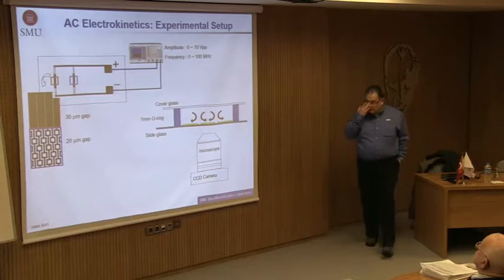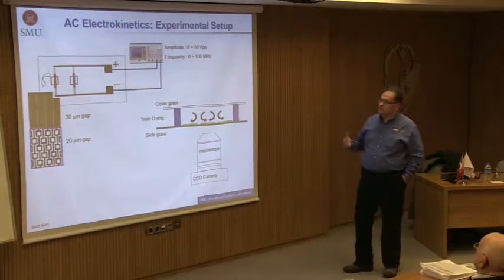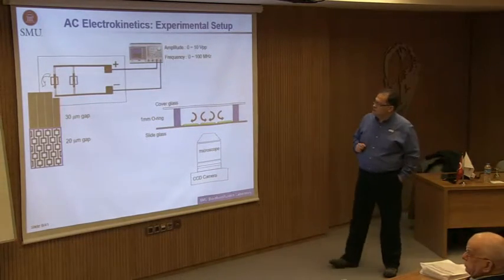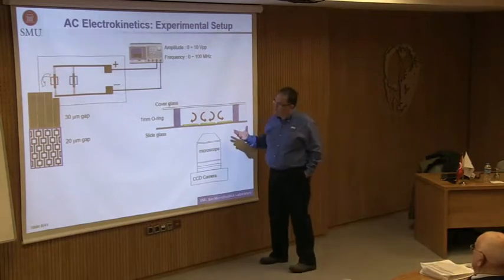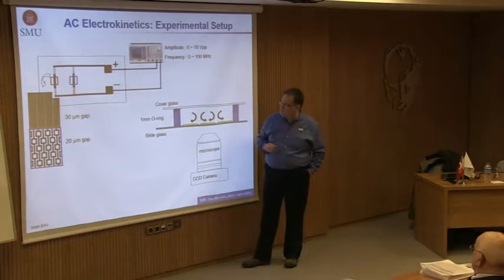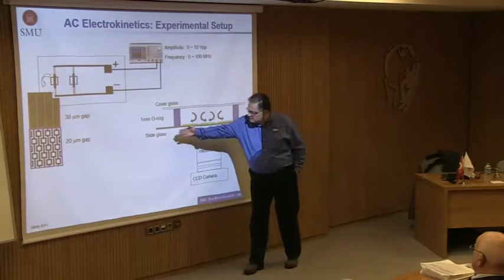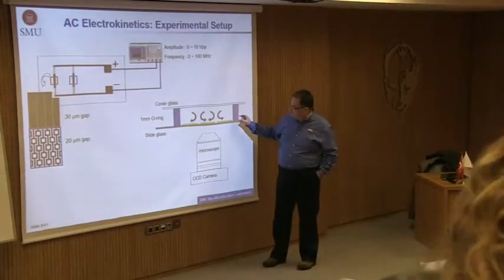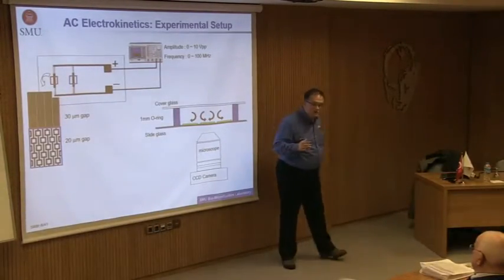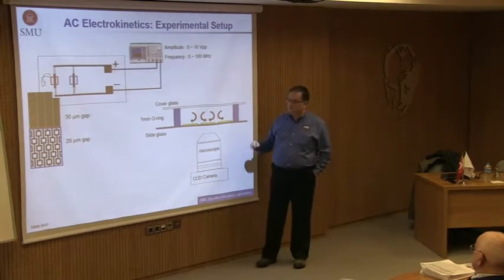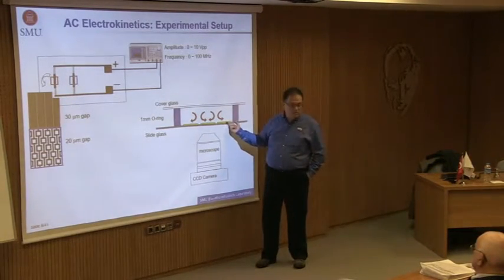But what happens if you start applying AC fields? What do you really observe? So everything I'm going to show you from here on is done in a very simple setup. Basically, we have a glass slide, and we sputter very thin electrodes on them. And this is as thin as maybe 20 nanometers of gold. So it's see-through most of the time.